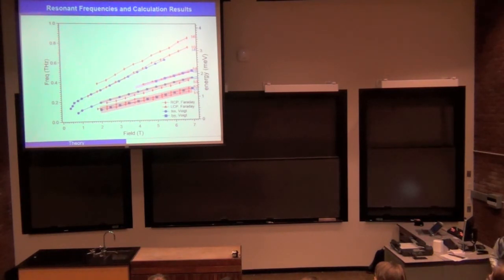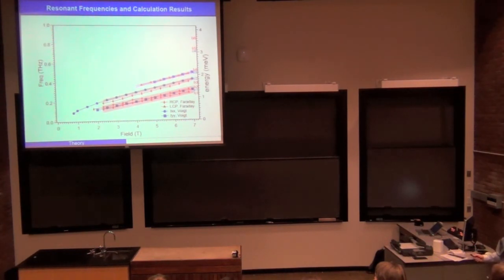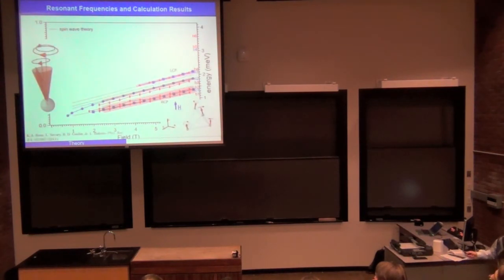And our collaborators did some spin wave calculations. It turns out these lower energy and lower g factor modes all belong to spin waves. And it is interesting that we see both a right circular polarized channel and also a left circular polarized channel. As I mentioned, when the field points in a given direction, you really expect absorption in only one of the circular channels. And why does that happen? Actually, it turns out the spin wave calculation can answer this question quite nicely. The ytterbium iron compound turns out to have an easy-plane anisotropy instead of Heisenberg-type behavior. As a result, the spin is not fully polarized by the magnetic field in the same direction. So you have the equilibrium position of the spin slightly tilted away from the field direction.